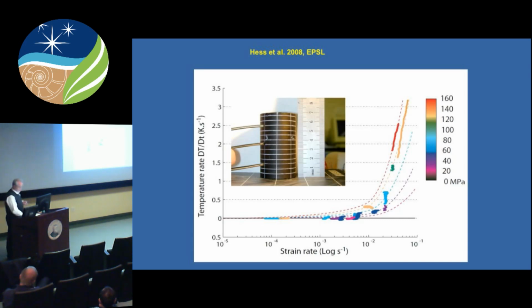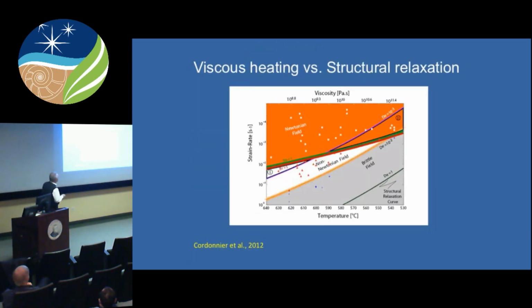And we can actually check those results by looking at the value of the viscosity which results from this, because we're deforming it as we do, and back calculating the temperature change we would need to explain the shift in the viscosity of the sample. And we do, and it works. And you end up with 2 fields which cross each other. You have a proportionality to the strain rate for the structural effect, which is what's destroying these things by fragmentation, which is quite different from that due to the